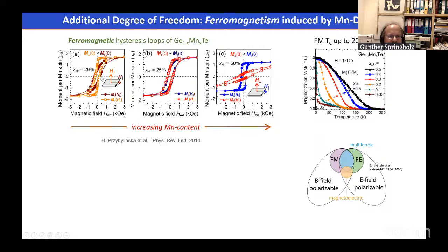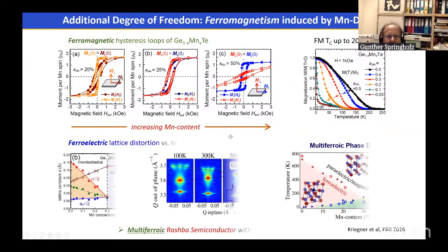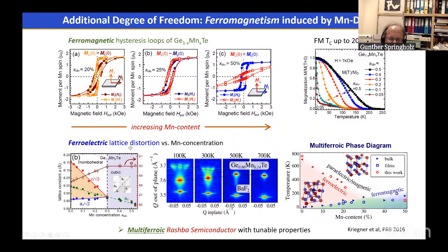And here are shown the corresponding hysteresis loops recorded at low temperature for layers with different composition. If we add manganese, we get a ferromagnetic response of the system, but on the other hand, adding manganese reduces the ferroelectric lattice distortion, as is shown here. So pure germanium telluride has a very large rhombohedral distortion, which is proportional to the difference between the in-plane and out-of-plane lattice constants along the 1,1,1 and perpendicular to the 1,1,1 direction. If we add manganese, the splitting decreases, and at some concentration around 30%, the system becomes cubic at room temperature, because this is measured at room temperature.